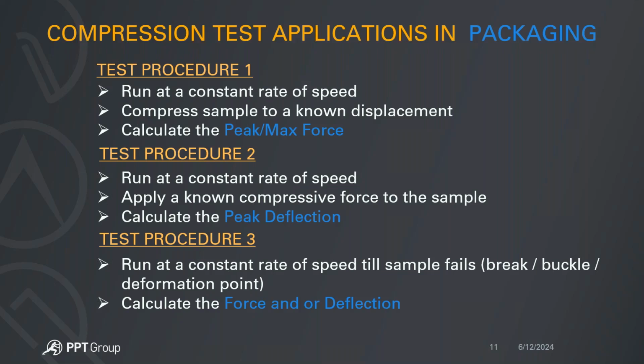If you're in R&D and you're just looking to learn as much as you can about a product, sometimes it might be necessary to run all 3 tests. So for instance, if you run test 1 and you compress to a known displacement of say a 1/4 inch deflection, and then you measure the max force, you can then run test 2 and say, well, if I apply this X force that we acquired from test 1, are we likely to see the known deflection from test 1? So there are different ways of running these tests, and again, your industry will determine which one of these tests you run, or sometimes you might run all three.